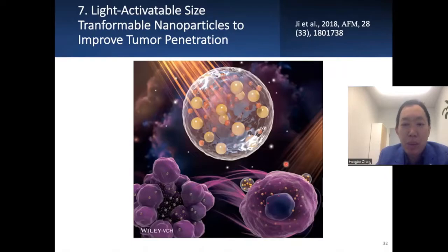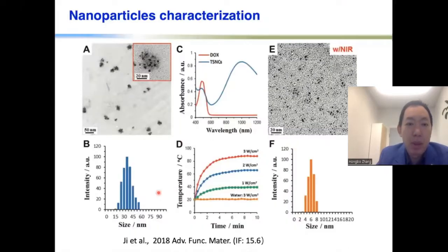But in order to have tumor penetration, the 100 nanometer is too big. So they cannot penetrate deep inside a solid tumor. So in that case, you will need a smaller size. So that's why we have this kind of design, where we can have an in vivo size transformation at the tumor site. For example, as you can see, here is the nanoparticle produced. We have some photothermal responsive particles, and then we load them into a polymer matrix. And then this will become a 50 to 100 nanometer size particle. And you can also have some drug in this polymer matrix.